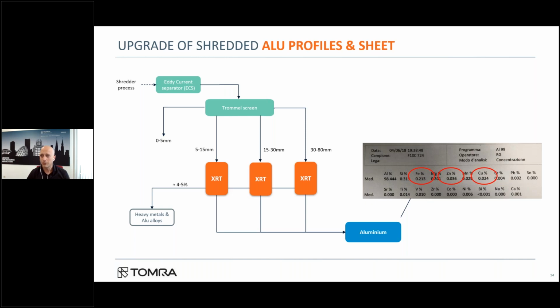The product from the eddy current is still contaminated with heavy metals and aluminum alloys containing higher amounts of heavy metals. And therefore, they screen the material into 3 different size fractions, and they remove the contaminations using 3 XRT units in parallel. The ejected fraction is about 4 to 5% of the input and can be further sorted, again, to recover the copper and brass. The aluminum product of the 3 sizes is then mixed together and sold to the remelter.